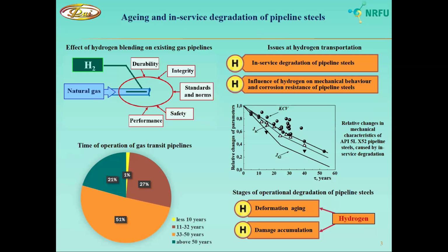Since a significant part of pipelines is near the end of their design life, in-service degradation implies embrittlement and deterioration of mechanical properties. So based on our previous results, two main stages of in-service degradation of pipeline steels were distinguished: deformation aging, and also in-bulk material damage accumulation. And also it was demonstrated that hydrogen plays an important role in accelerated degradation on both stages.